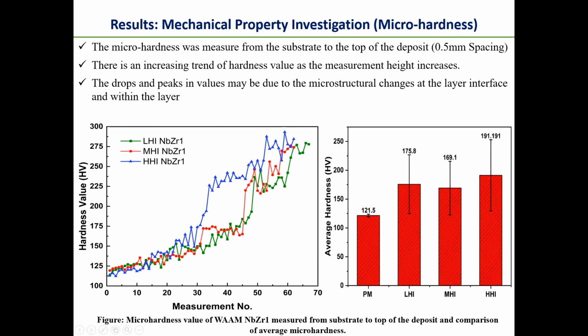And after that, we measured the microhardness from the bottom of the substrate to the top of the deposit at a spacing of 0.5 millimeter. There is an increasing trend in the hardness value as the measurement height increased. This may be due to the different microstructural change or due to the dendritic arm spacing. There are some drops and peaks in the values. These are due to the layer interface and within the layer where the indenter was. The average microhardness value in the low heat input case was 175.8, in the medium heat input case it was 169, and in the high heat input case it was 191.19 HV.